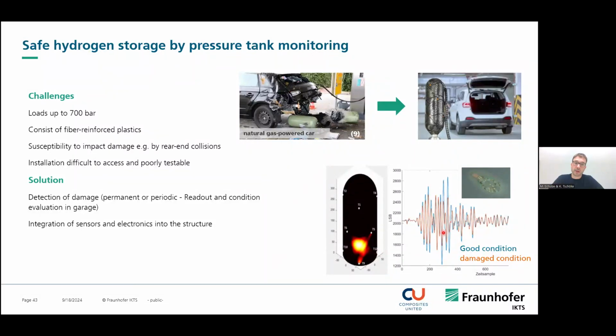Here on the right side, you can see the same principle as on the previous slides. We measure in different conditions of the structure, the so-called good condition, the condition without any damage, and the condition with a damage in it. And then by comparing them, you can also get information about possible impacts on your pressure vessel. In this example, we have different positions for the transducers. They can be embedded even in the pressure vessel. But how to get these positions?